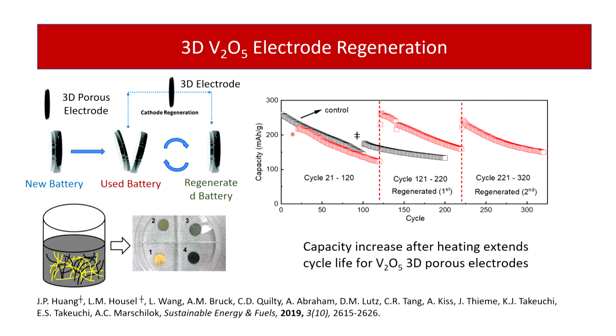And so one set of experiments that we did was developing fibrous materials. In this case, the active material is vanadium oxide, combining it with a carbon fiber for conductivity. So this is a self-standing, self-supporting porous electrode with no binder present. We cycle, then remove the electrode from the battery, simply rinse it off, put it in an oven, bake it at 200 degrees for a couple hours, put it back in the battery. And you can see that the control, where we just rebuilt the battery, doesn't see the level of improvement that we see with this regeneration process. And in fact, we can regenerate these electrodes over and over.